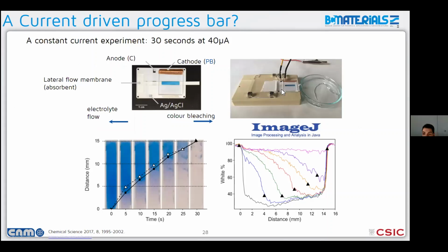I mean, this was the setup. We have some solutions in here that we can change and flow through the system through this lateral flow system. We have an absorbent pad, which is just a paper towel, and this is what we saw. So first we characterized the system by passing constant currents, by polarizing at different potentials, and the image analysis we did using ImageJ.